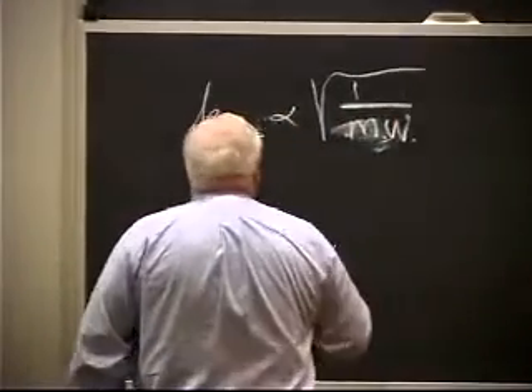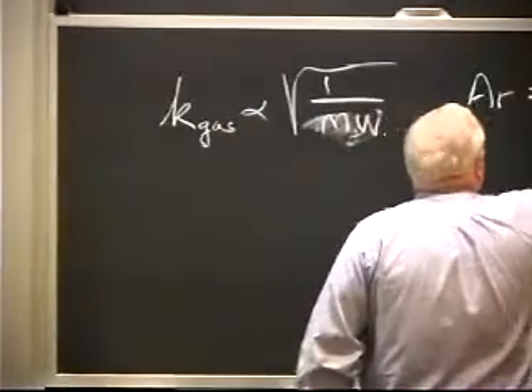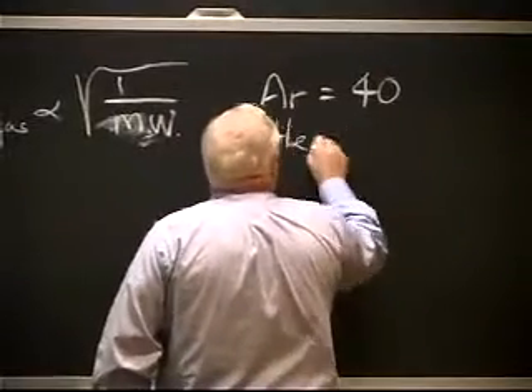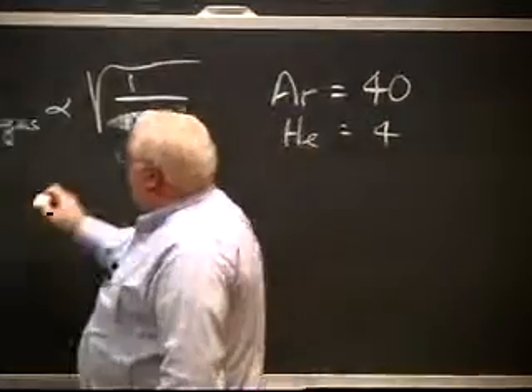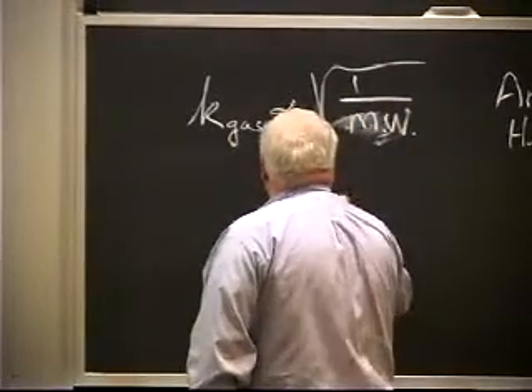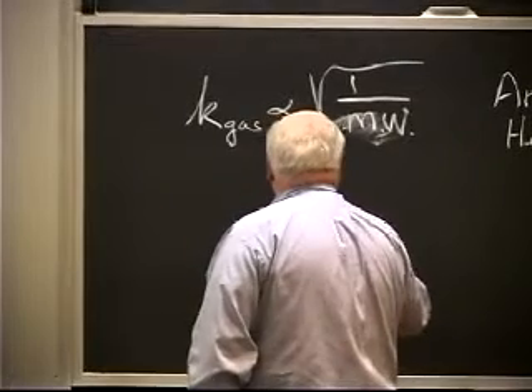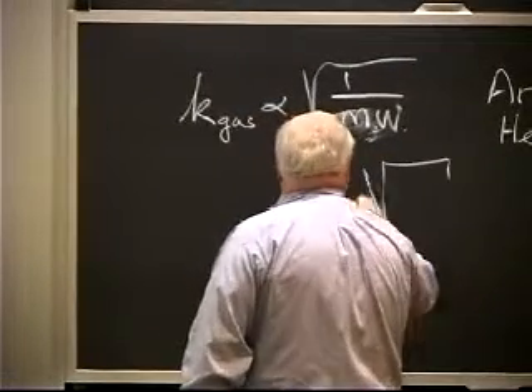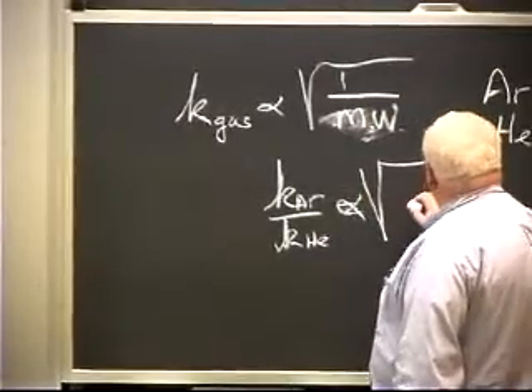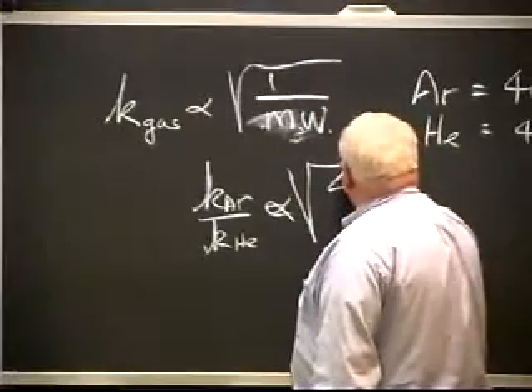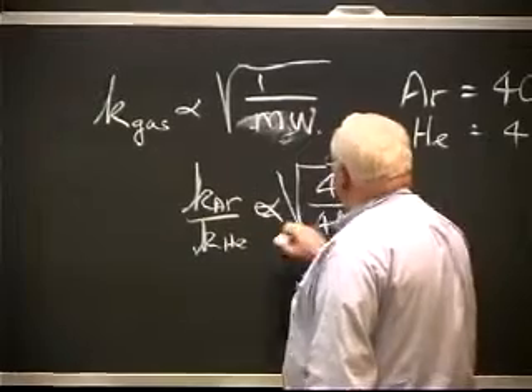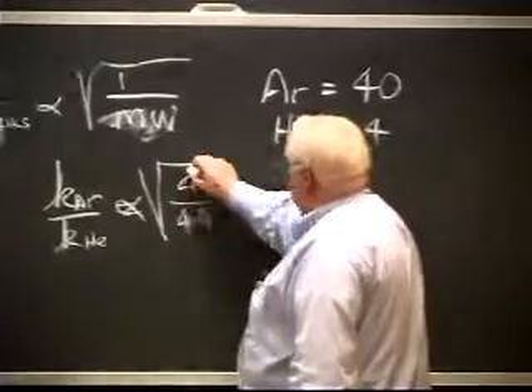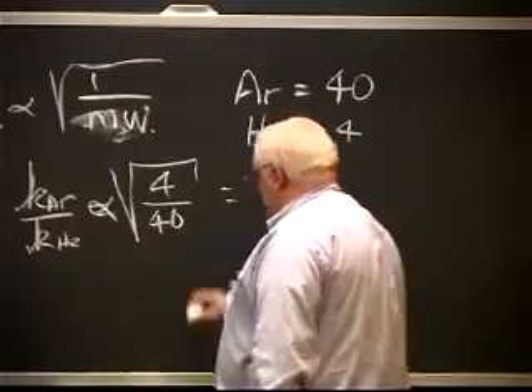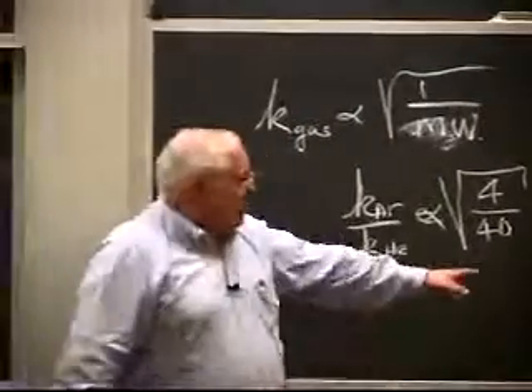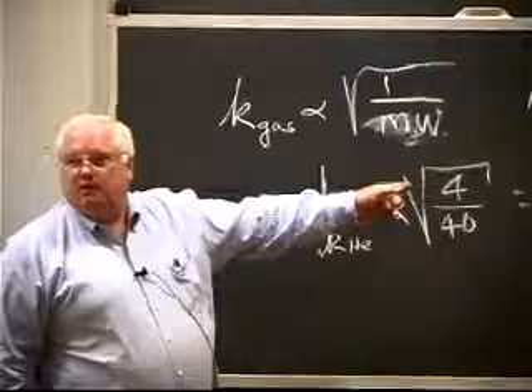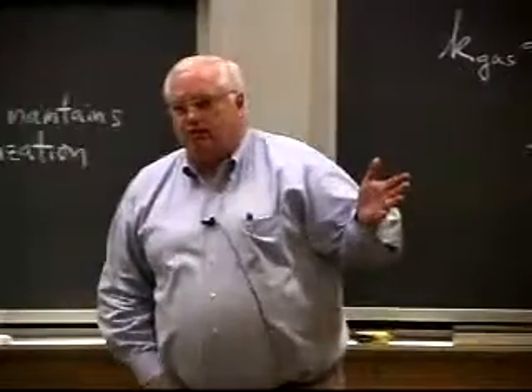It turns out for argon, the molecular weight is 40. For helium, the molecular weight is 4. So the ratio of K of argon to K of helium is proportional to the ratio of their molecular weights, which is, in this case, 4 over 40, because it's the inverse, right? And that's 1/10, and the square root of 1/10 is about 1/3. Helium has 3 times the thermal conductivity of argon just because it's a lighter element.